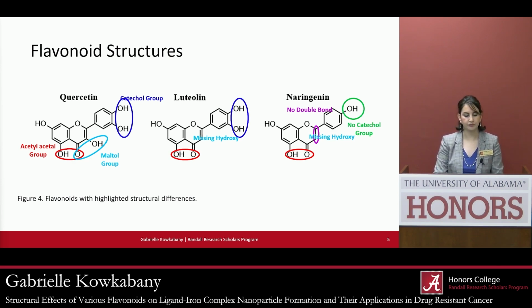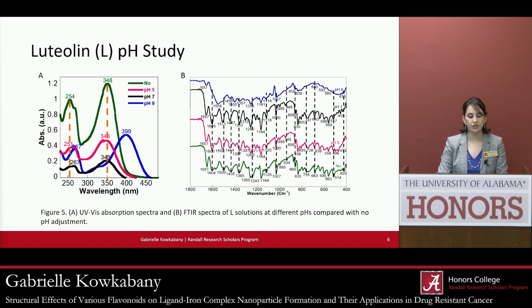And so in light of these structural differences, I wanted to understand the pH-dependent stability of these flavonoid structures. And so I did this with luteolin and naringenin by putting them in solution with no pH adjustment, a pH of 5, a pH of 7, and a pH of 9, and looked at their UV-vis absorption spectra in addition to their Fourier transform infrared spectra.